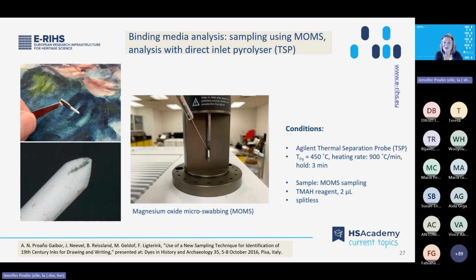So I used a technique called magnesium oxide microswabbing, or MOMS, and it was developed by A. N. Proaño Gaibor at the Rijksmuseum, specifically for sampling thin paints and inks on paper. The tiny particles are removed from the surface using the shaped tip of a thin magnesium oxide rod. And that I place directly into a pyrolysis tube, treat it with TMAH, and the whole thing is pyrolyzed. The MOM sticks are inert and they can be reused indefinitely. So for this study, the MOM sampling and then the subsequent PyGCMS was useful for the characterization of the binding medium, as well as the identification of certain organic pigments.